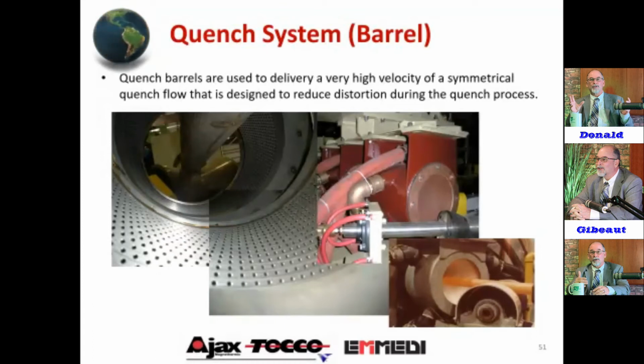It's a big value to have a very aggressive quench. You can see they're angled on a 30-degree angle in the lower left corner with that quench water on. And you can see the big hoses all the way around through the 4 baffles inside to get the uniformity and to be able to adjust around it. That's how critical this is. This is where the work is done. This is where your metallurgy is either good or bad. I mean, everybody can heat uniform for the most part. It's right here in this quench. So we have what we believe is an economical best solution, and it's been proven over decades and decades.